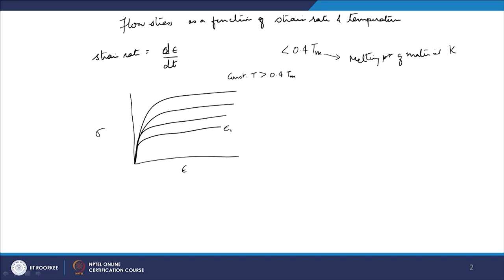That they are at different strain rates. Okay, they are all at different strain rates. And from their flow stress values, I can say that epsilon dot 4 is more than epsilon dot 3, more than epsilon dot 2, more than epsilon dot 1. Okay, so the lower the strain rate, the lower the flow stress. Okay, the higher the strain rate, the higher the flow stress. Okay, so if I want to give a relationship to this kind of effect of strain rate on the stress, a very generalized